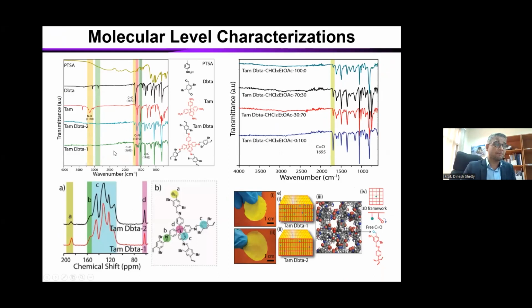If you look into the FTIR, in the case of the membrane with hydrophobic nature, you have more carbonyl groups. The carbonyl group is coming from this aldehyde linker. On the other hand, in the case of the less hydrophobic system, you have more imine bonds, which means a more conjugated system. What does it suggest to you? It says that in one case we have more defects compared to the other case, which means we are breaking to make it. We are introducing more defects just by changing the biphasic solvent system.